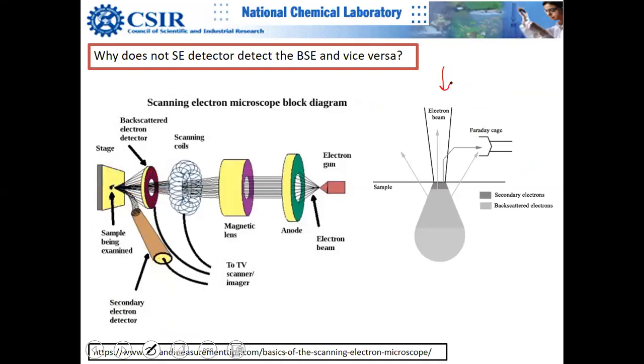For example, with 20 keV primary beam energy: backscattered electrons are the same primary electrons that are kicked by the nucleus like a slingshot and change direction without any energy exchange — elastically. So 20 keV in and the same energy electron comes out. They retain very high energy.